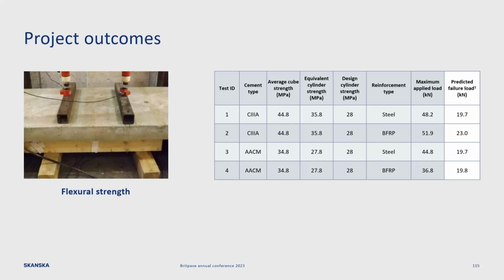So you can actually see from this that both the basalt fibre reinforced slab and the steel reinforced slabs performed very well. And I was quite pleased about that, because it demonstrated that although you have a different E-value, as we've just heard, and a more fibrous nature within the basalt fibre reinforcement, the performance when in the matrix of concrete was very good.